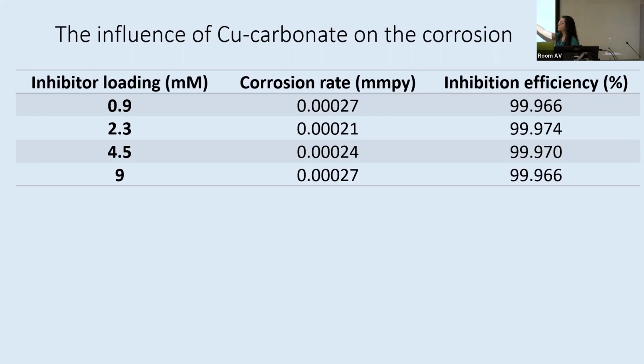So with an inhibitor loading of copper carbonate, we get effectively no corrosion, and you can see nearly perfect inhibition efficiency. So this is talking about, as you can see, 9/10 of a millimolar in a solution of 5 molar MES, and we still get fantastic results. Now, these are consistent with what's been seen in literature. And if I show you, you'll see from the ICP, we have no iron, we have copper, right? So all these things make sense, but they also don't make sense.